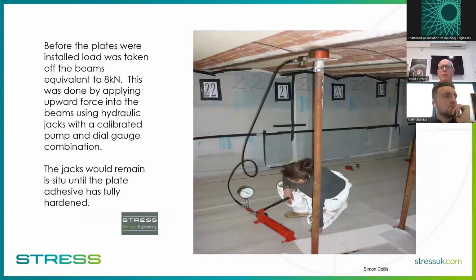But before we started actually putting the carbon fibre sheet up, we jacked a little bit of load out of the balcony. So you can imagine the balcony under load, it will actually, by a few millimetres, depress in the middle, even though those beams are incredibly stiff. So we only jacked 8 kilonewtons, 0.8 of a ton out of each one, but we did every single one and maintained that through the application of the carbon fibre.